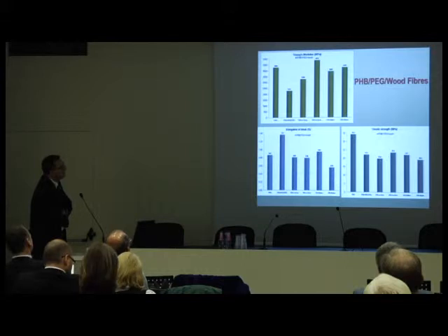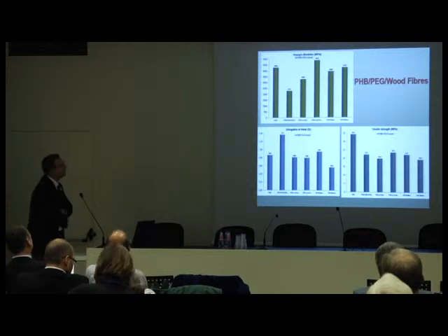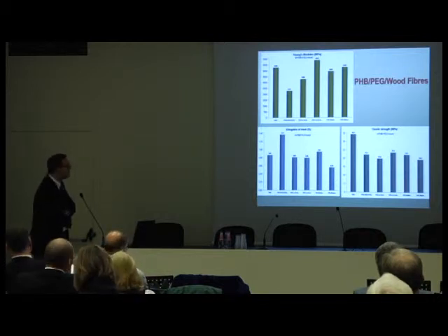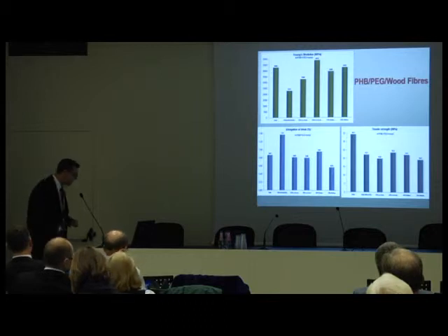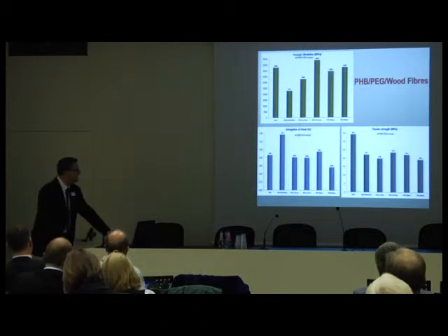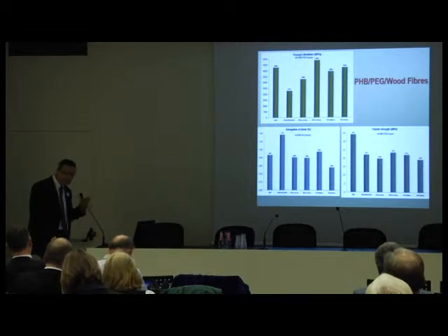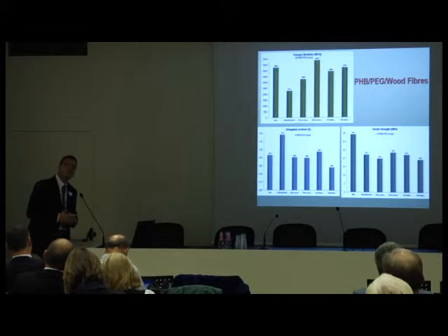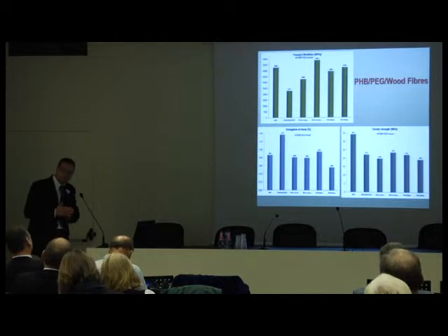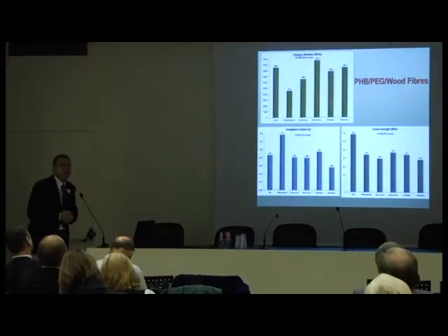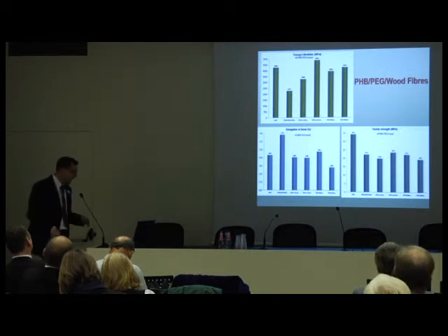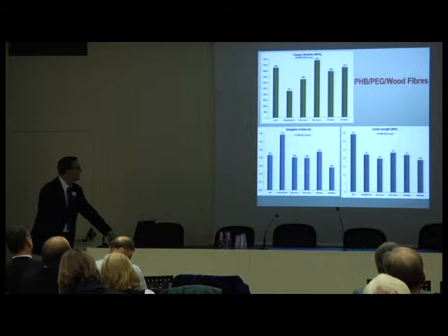And we found that it's not an easy task, because pure PHB is, in fact, very brittle. It's a very brittle material. And even with PEG, the properties improve very little compared to PLA. So that is why PLA is so successful at the moment: it's easy to modify and obtain a better material suitable for application, while PHB is much more difficult to work with, unless you rely on a formulation from a private company that you don't know exactly what's inside.